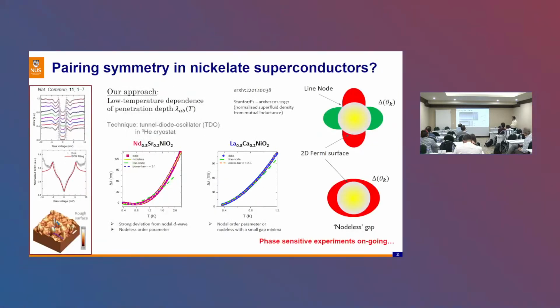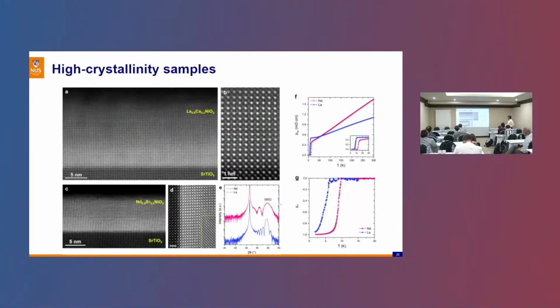All right, so at least having these so-called quality samples, now we have been able to produce them and also try to do different experiments. So in the next 2 slides, I'm going to discuss 2 main experiments that we have done recently. So as you can see, again, the lattice fringes, quite good high resolution TEM data, relatively sharp transitions, and you can observe DC diamagnetic response directly from this high quality sample.